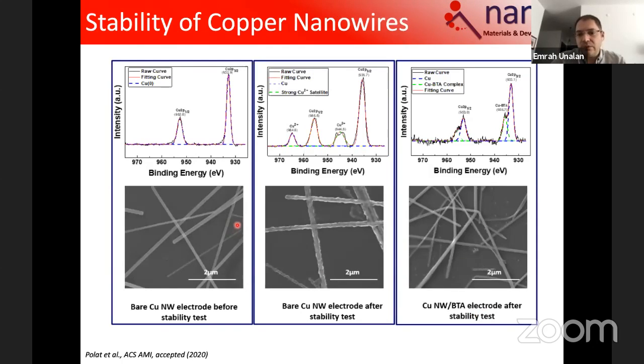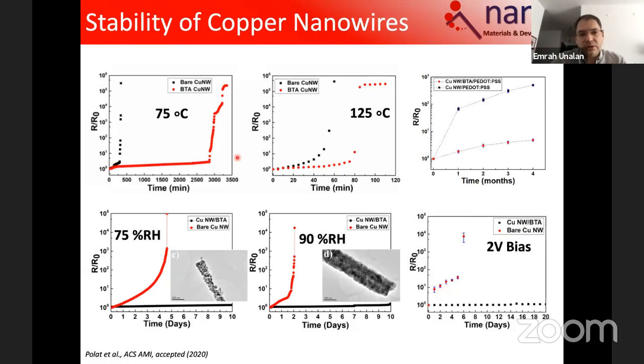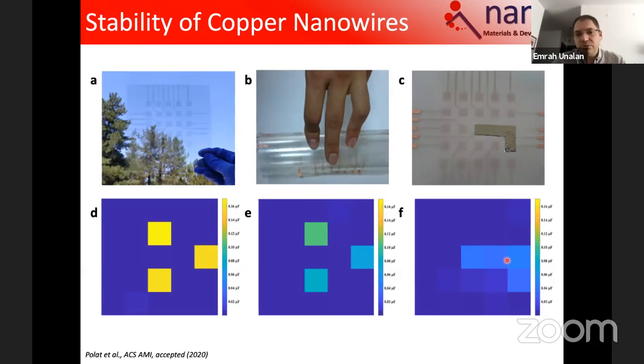And spectroscopically, we also monitored that, for instance, if you don't put the BTA, the dimples come along, and the smooth surface gets distorted. But when you put the BTA, the surface is well protected, which is also dictated by the resistance measures upon the BTA deposition. And as we did for silver, we looked into the temperature stability, humidity stability, stability under PEDOT:PSS, and voltage bias stability. And in all these measures, it is very highly performing compared to the non-BTA deposited copper nanowires. And in order to put everything into context, we also demonstrated a capacitive touch sensor. And as you see, it's like a multi-touch, as we use these days in our cell phones. If you touch with a conductive object, that can be a finger or an aluminum foil, it detects the location, and it can be bent because it is on flexible PET substrates and works perfectly.